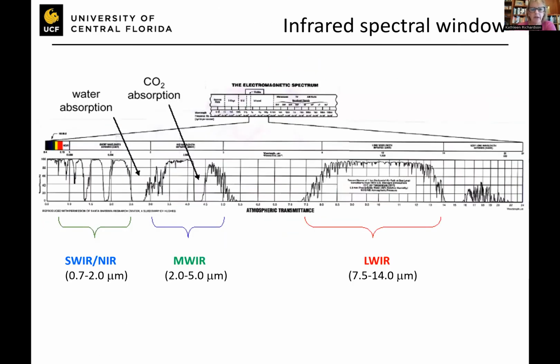So let me just redefine these spectral windows again. Here's a slightly different image of the same information, but I want to define the three different regions. People argue about what the specific cutoffs are, and I don't want you to get sidetracked on these, but typically the SWIR, shortwave infrared or the near infrared, is typically in this lower wavelength, higher energy region, and it typically overlaps with a little bit of the visible. So if you remember, your red helium-neon laser pointer transmits at 0.63 microns or 632 nanometers in the red. And typically it's the end of this visible region to about 2 microns or 2.5 microns that constitutes the SWIR. We typically talk about the mid wave as the mid region, the 2 to 5 micron, and the long wave is the 7.5 to 14 microns. Sometimes this is 8 to 12, 8 to 14, depending on who's trying to do what with the material.